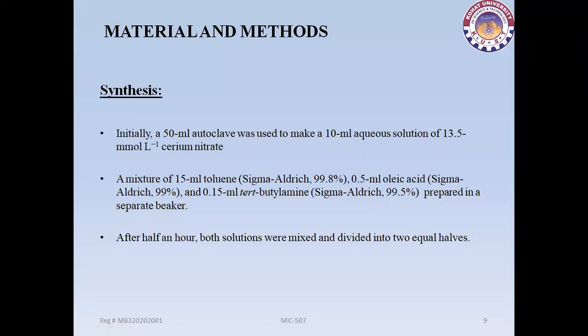Material and methods. There are several steps and methods. First one is synthesis. The cerium oxide nanoparticle were synthesized through hydrothermal approach. Initially, a 50 ml autoclave was used to make 10-ml aqueous solution of 13.5 millimolar per liter cerium nitrate. A mixture of 15 ml toluene, 0.5 ml oleic acid, and 0.15 ml tert-butylamine was prepared in a separate beaker. After half an hour, both solutions were mixed and divided into two equal halves.